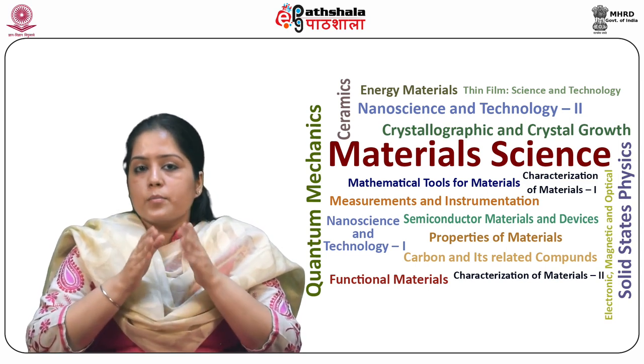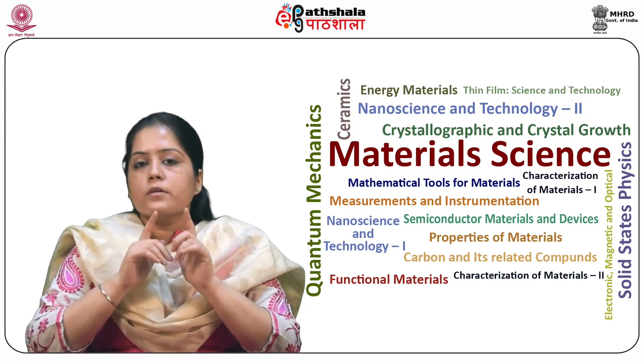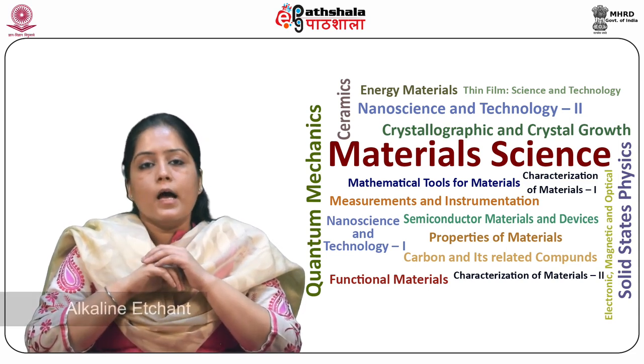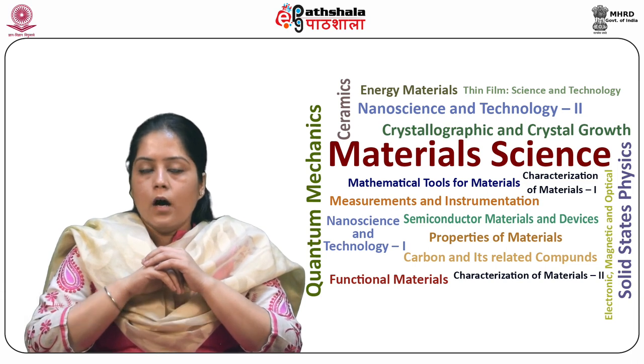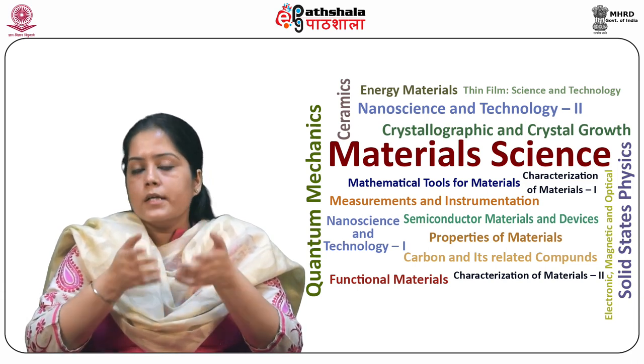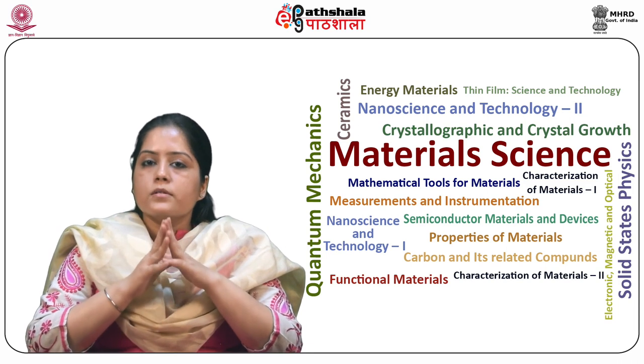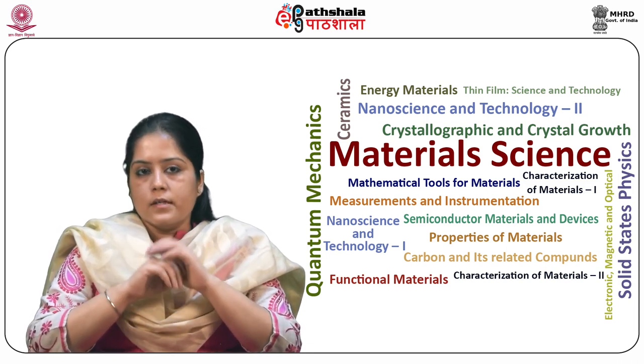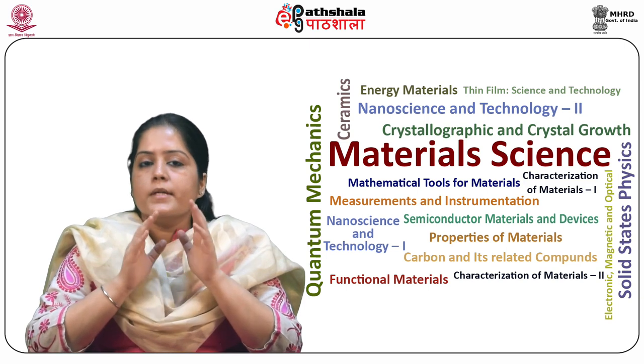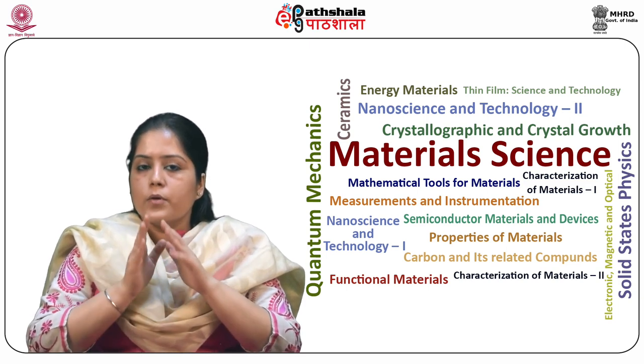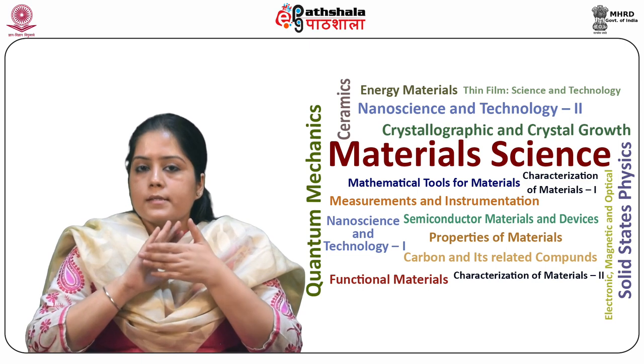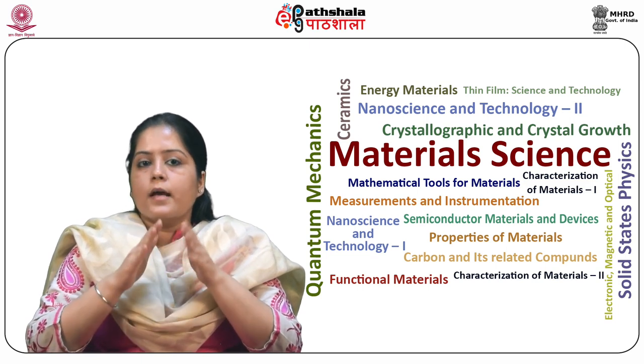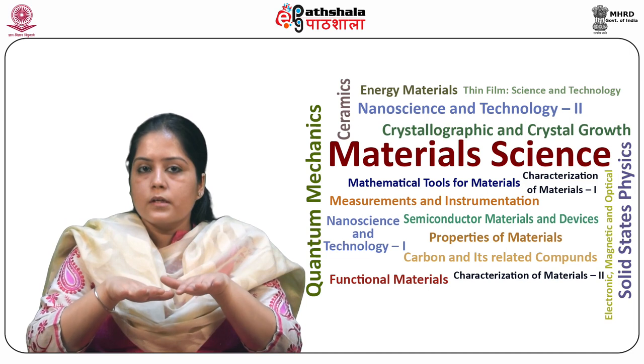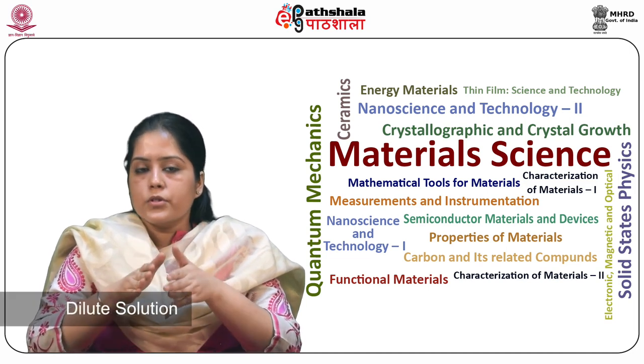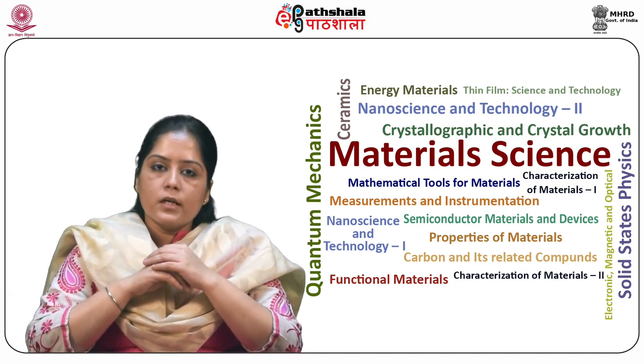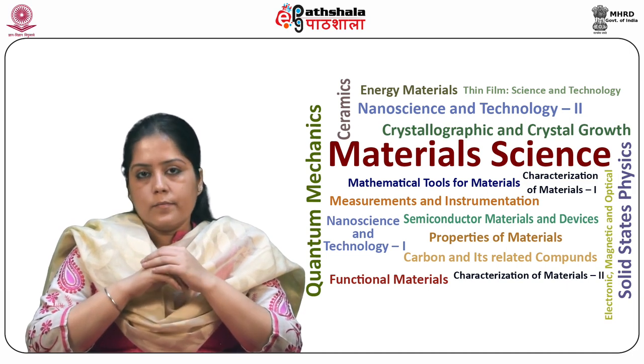The less expensive and most common etchant is the alkaline etchant. However, it is orientation dependent and works well for 100. Metallic contaminant impurities from silicon surfaces can easily be removed using a dilute solution of HNO3 or HCl.